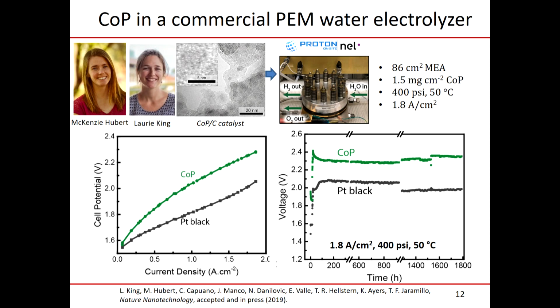They've already put the sunk cost into a nuclear reactor that's portable in the sub, and dialing up the nuke to give a little more electricity costs them marginally nothing. So for them, CapEx is everything. So they wanted non-precious metal systems in electrolyzers. So we worked with Proton Onsite. This is a commercial-grade system. They literally sell this with platinum and iridium. It's an 86 square centimeter membrane electrode assembly. It's 400 psi output pressure of hydrogen, 50 degrees C, and is driven at 1.8 amps per square centimeter.